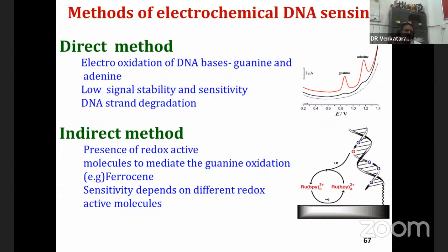the double helical formation. The criterion required for this transport is that the base difference between these two is 0.34 nanometer. That means the distance between these two bases should be around 0.34 nanometers, so that the purine and pyrimidine bases mingle together, and they are able to make an electronic cloud, through which your electron charge transfer could occur. If no charge transfer can occur, then this metal signal will not be diagnosed.